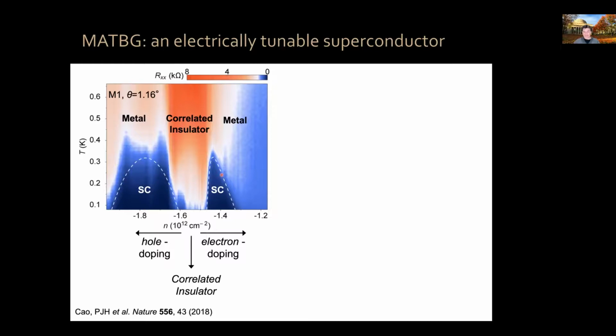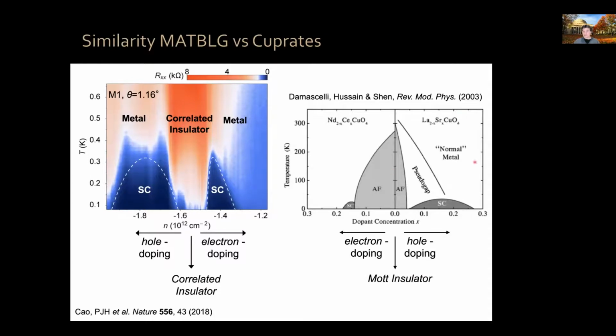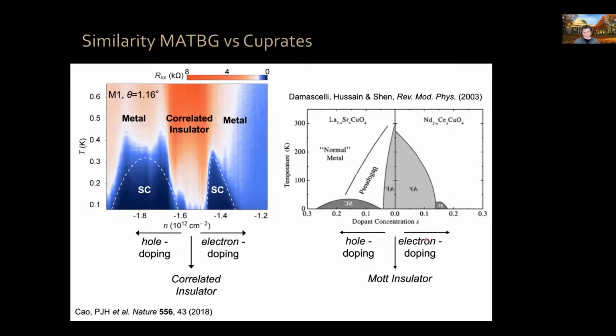Now, when my students showed me this data, immediately it reminded me of the hundreds of times I have seen phase diagrams such as this. This is a phase diagram of the cuprate superconductors. At zero doping, you have a Mott insulator state. That actually means 1 electron per unit cell. In our case, it happens that we have a correlated insulator state at 2 electrons or 2 holes per moiré unit cell. And now let me flip this axis so that they are identical to here. As you can see, if they hole dope, they have a large superconducting dome. If they do electron doping, they have a smaller superconducting dome, very similar to this behavior.